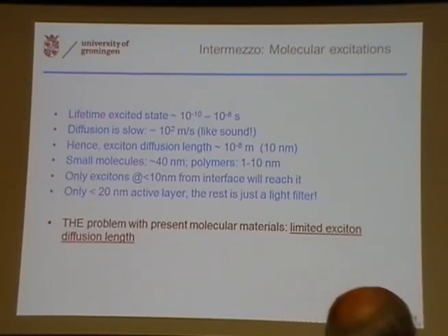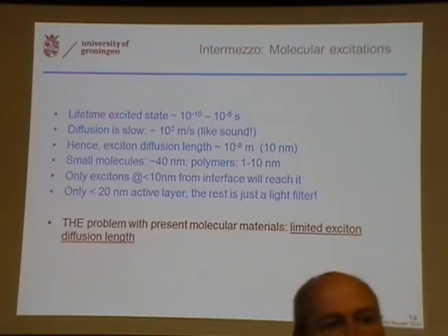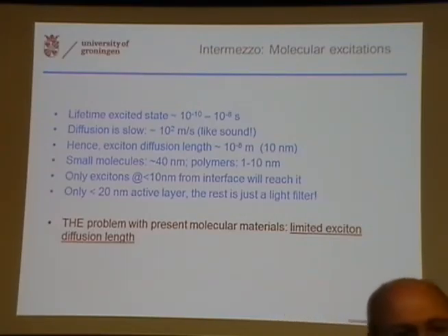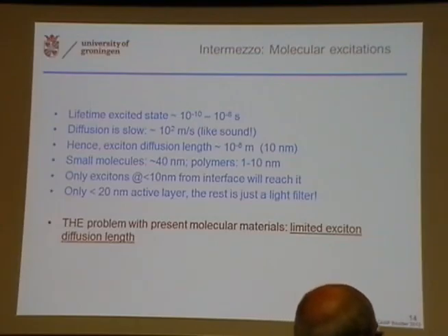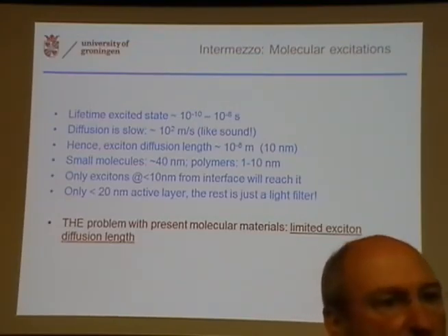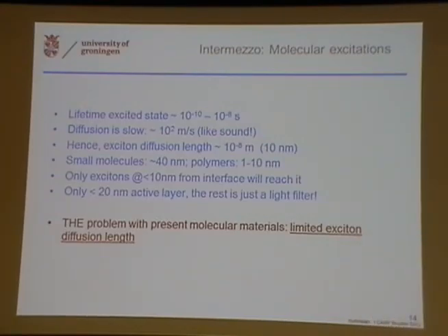And so now you can calculate that the exciton diffusion length is something in the order of 10 nanometers. And if you have very high quality crystals, maybe you can get 15 nanometers. But especially in these disordered materials, it's more likely that it's 4 nanometers, something like that. So only excitations that are closer than 10 nanometers from the interface will make it to the interface and lead to charge separation.